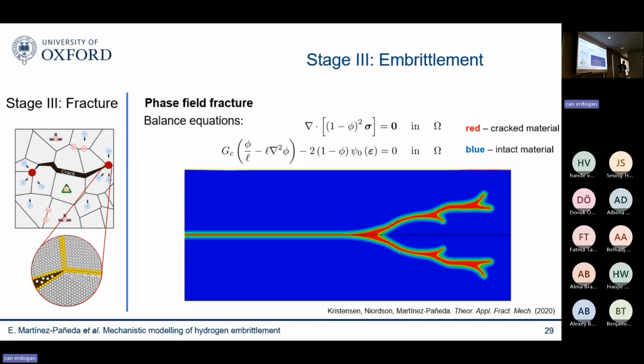And then you have another equation that describes the evolution of this phase field. This is basically a competition between the energy stored in the material, which depends on mechanical straining, and the fracture energy, the toughness, a material property that we can easily measure. And just by solving this differential equation, you can capture very complicated cracking patterns on the original finite element mesh and without any convergence problems. The method is very robust.